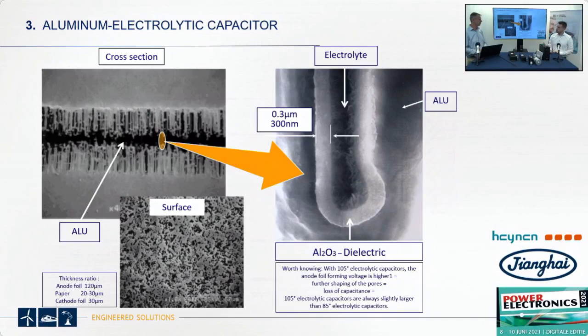Does this also have to do with voltage breakdown? Yes. You need this oxide layer so that you don't get a voltage breakdown. Okay. And therefore you need a thick oxide layer to resist the voltage. Okay. And when you use the capacitor at 105 degrees and not at 85 degrees, then you also need a thicker oxide layer to resist the temperature and the voltage together.